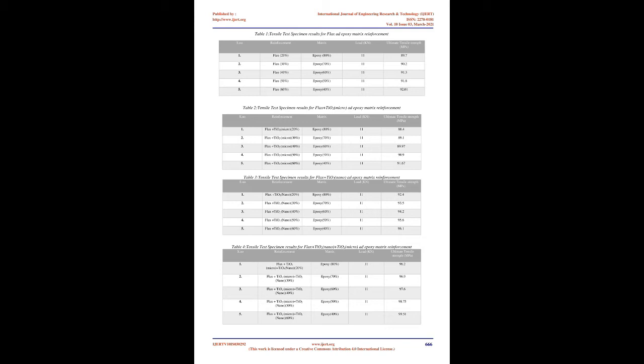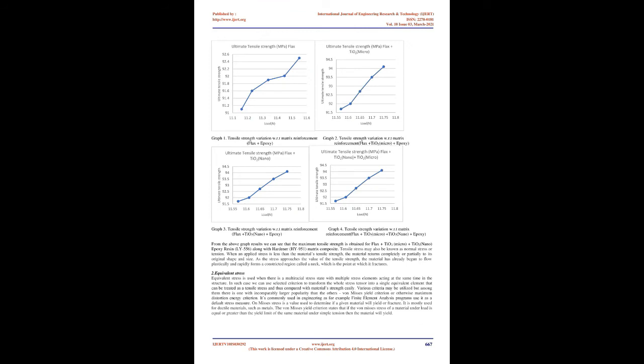The finite element method, FEM, was utilized to model the behavior of a material on a micromechanical level. The model was considered to be an isotropic material with a rectangular section of a beam. This section is then modeled in three dimensions using volume elements to represent the composite. Every element will have an isotropic property and will be situated corresponding to the fibers, and the matrix regions are coarsely meshed, merged together. The model is treated as a linear isotropic problem. The FEA model is comprised of Solid 95 elements, utilized for the fiber matrix structure as shown. The model included the fiber, matrix, and fiber matrix interface. Nine filaments were modeled in the surrounding matrix. The filaments with surrounding matrix were selected for stress investigation in this model. These regions were modeled using the coarse mesh, merged arrangement, as shown in the figure, and the load applied at the top edge of the model.